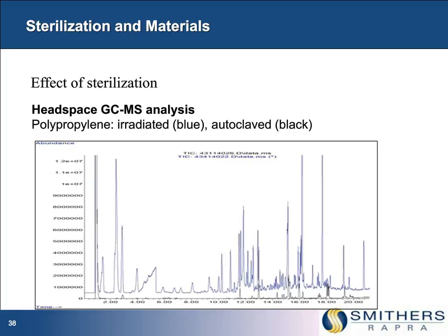So looking at headspace GCMS analysis, we're looking for the very volatile extractable species, using polypropylene as the material. So we irradiated the polypropylene and we also autoclaved it. And you can see from the plot the amount of chemical species and the number of them that we're seeing from the irradiated sample is very, very high. Polypropylene is not something that we typically want to irradiate. Because of the actual process, you do tend to see more volatile species, hence a different analytical approach to see those with the headspace analysis.